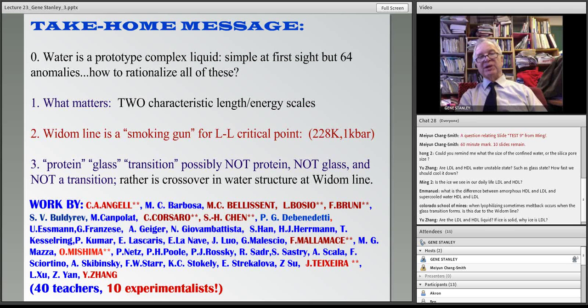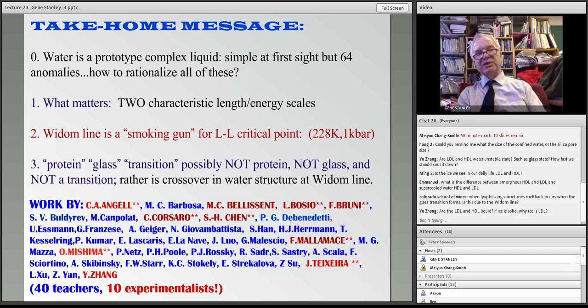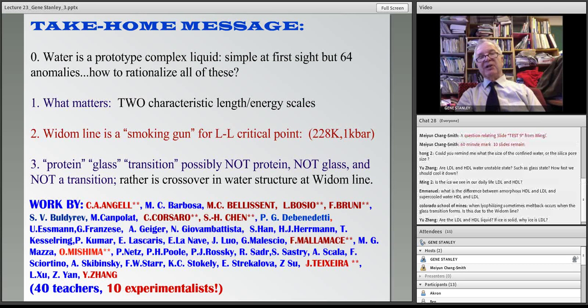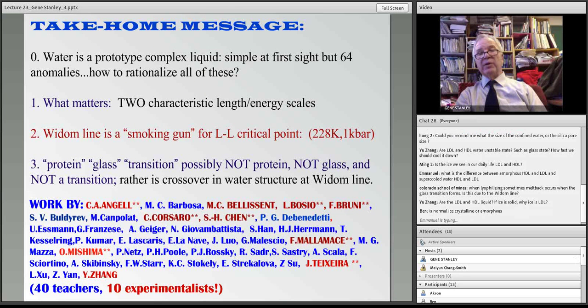Silica glass and molten silica are effectively the same, as we know, because if we watch a glass blower make a glass object that you buy in a fair to give to your friend, then you see the liquid silica plunged into a bucket of cold water, quenching the motion of all those little particles so they stay in place and form a glass. The same way that LDL is made by quenching water. And so the answer is LDL and HDL are liquid, but at the right temperature become a solid. If you cool slowly, you get a crystalline solid called ice Ih, and the local structure of LDL is the same as the global structure of ordinary ice tray ice in your refrigerator.